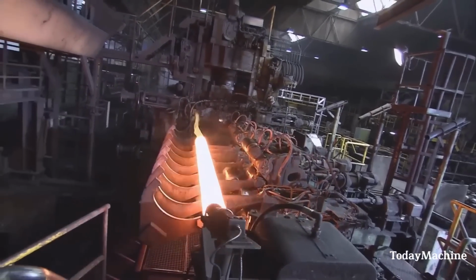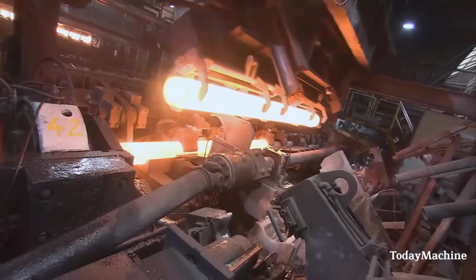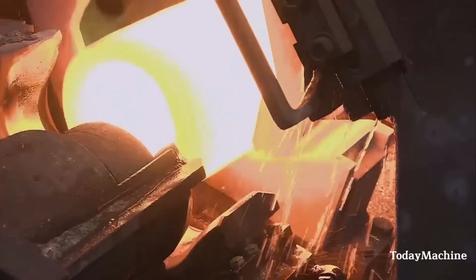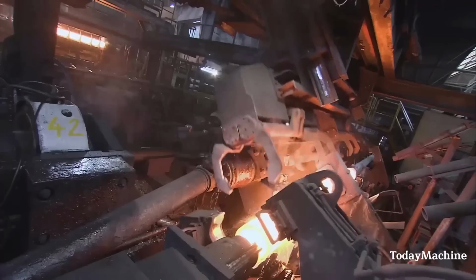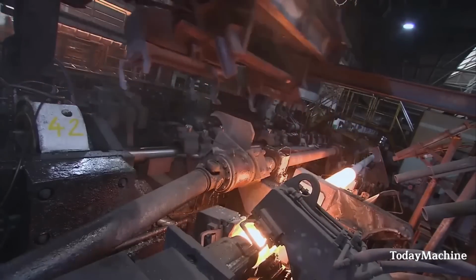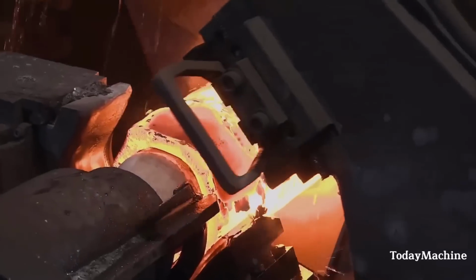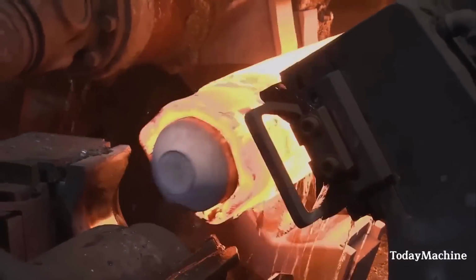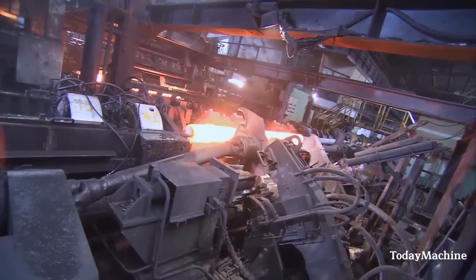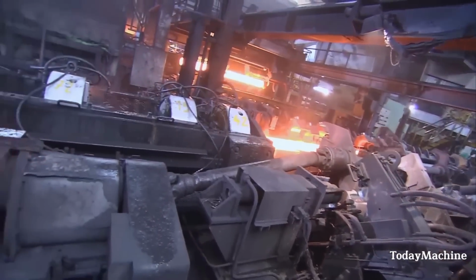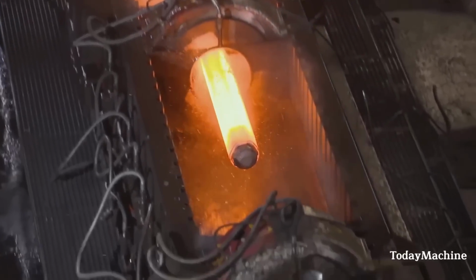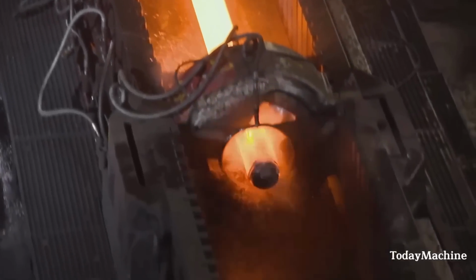The tube shell and the mandrel bar are pushed through a stand of forming rolls, elongating the pierced shell along the length of the mandrel bar, creating a seamless tube. This process can elongate the pierced shell up to 17 times its original length, resulting in a hollow tube. These hollows can reach lengths of up to 22 meters with a minimum wall thickness of 3 millimeters.